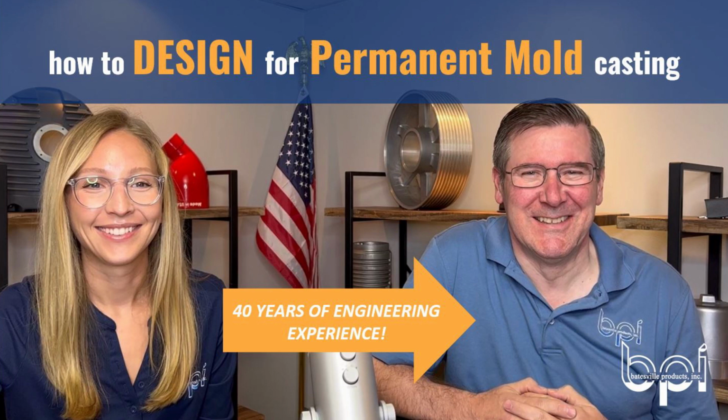The standard that we're talking about today is at least 30 thousandths of an inch. The radiuses make the part stronger. I'd give a preference to a radius over a fillet just because the metal flows more smoothly through a radius than it does through a fillet. Sharp corners in the final product, of course, cause high stresses, cracking, and possibly tearing of the actual part while it's solidifying, if it hangs up anywhere on the mold and doesn't release properly and at the right time from the mold. I would try to aim towards the thickness of the material as a radius wherever possible. You don't want to go too big with the radiuses, and you don't want to go too small. Okay, that's good to know.